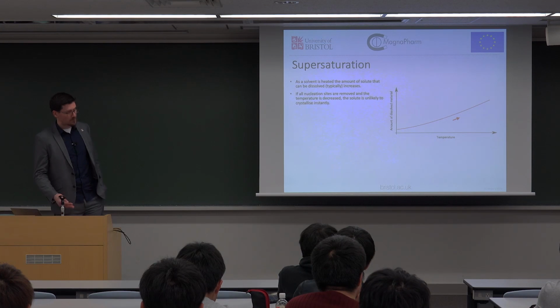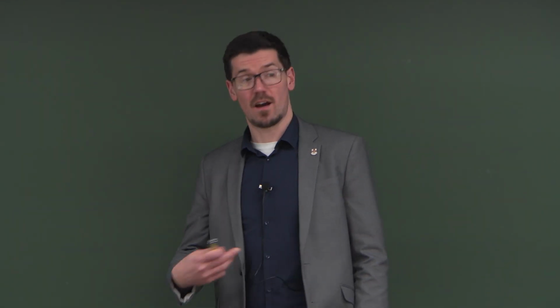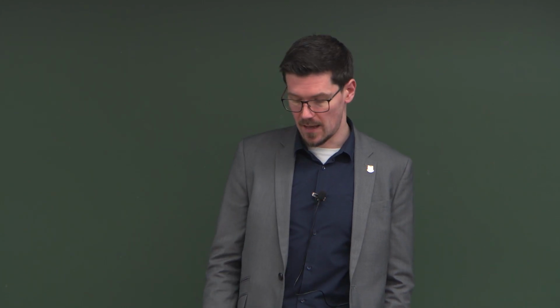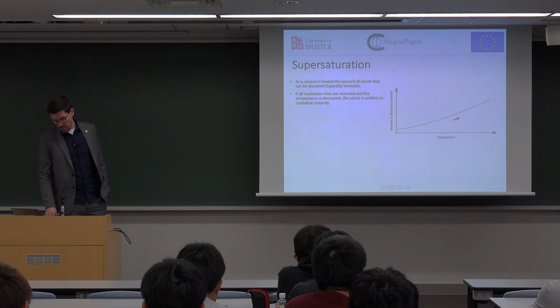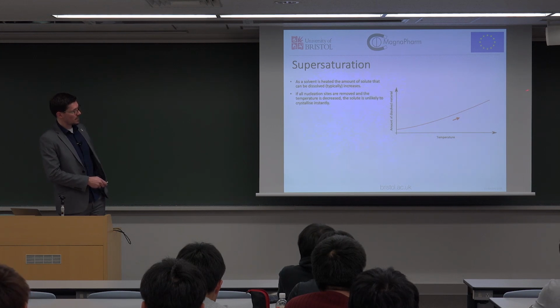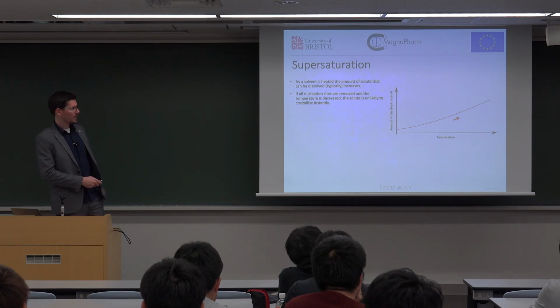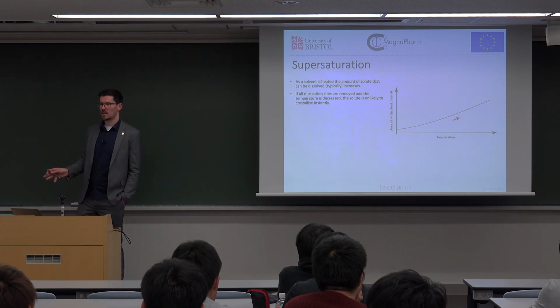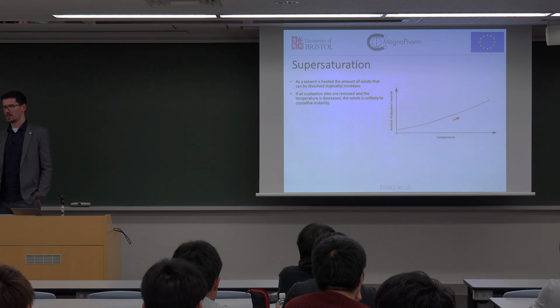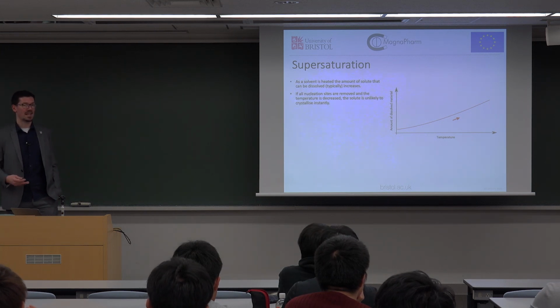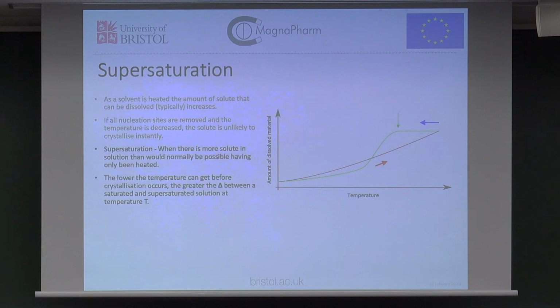So effectively, just to summarize where I think the mechanism of this lies, because we're still not at the bottom of it, is we dissolve material up to a saturation point, and then we remove any nucleation sites that we can. So we filter with the smallest filter we can, keeping the temperature elevated. Then we make it sealed and we start to cool. So we get this supersaturation again, but we're able to push the supersaturation further and further down the temperature gradient.